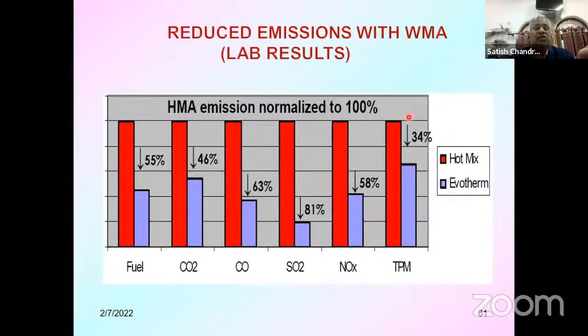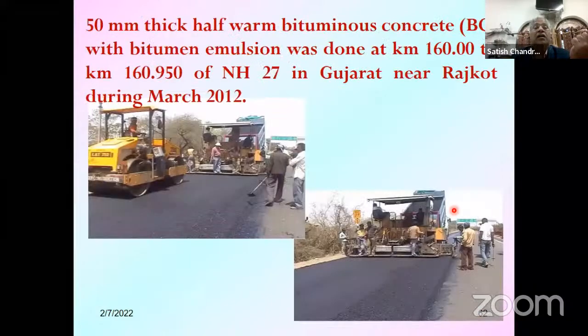And these are the lab study result. When you compare HMA mixes with warm mix mixes, the emissions, the fuel requirement, the CO2, CO, SO2, everything reduced. And Evotherm basically is an additive which is commercially available in the market to be used. And very small amount, sometimes 0.5% by weight of bitumen. And this is one section on NH 27 in Gujarat, which was laid in March 2012, half warm mix binder with bituminous concrete. But half warm mix is not so popular as warm mix.